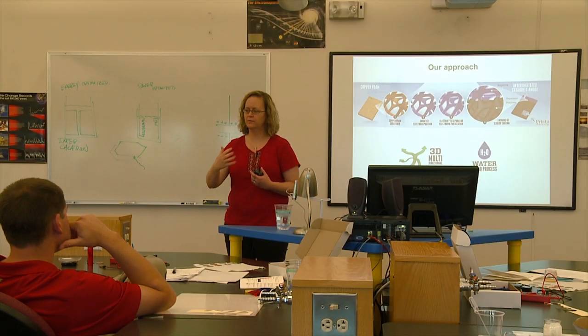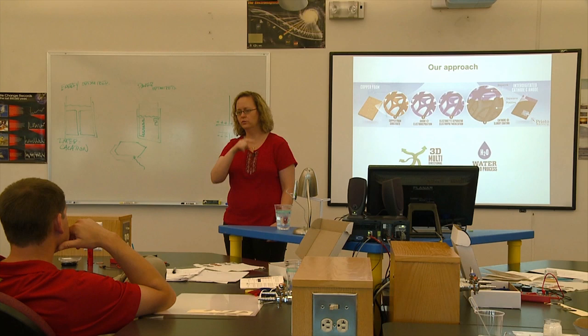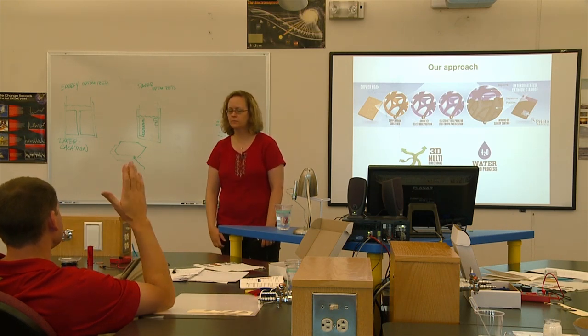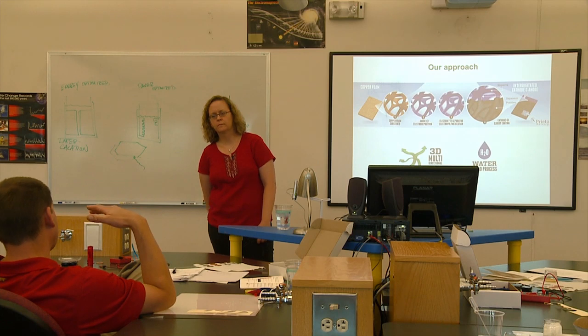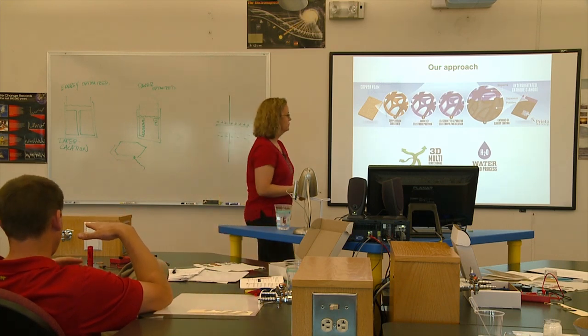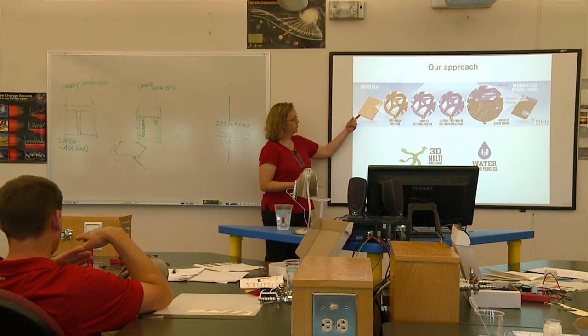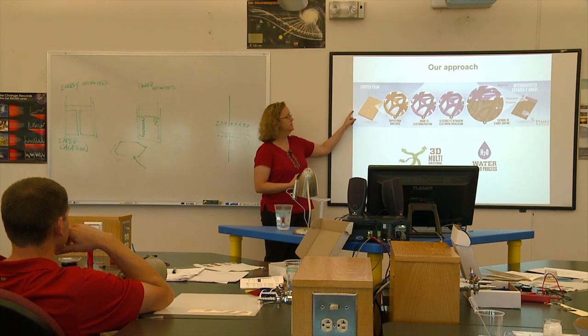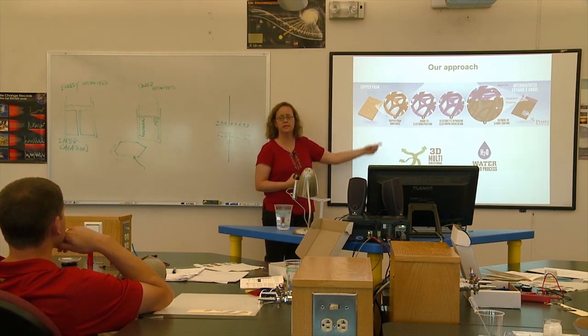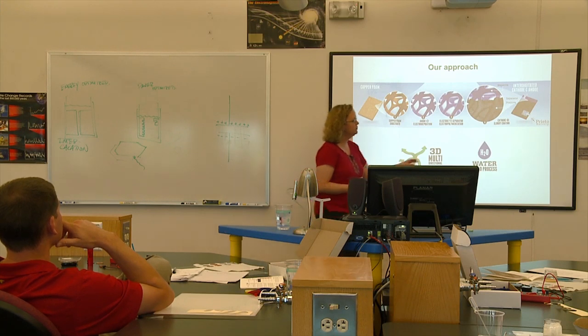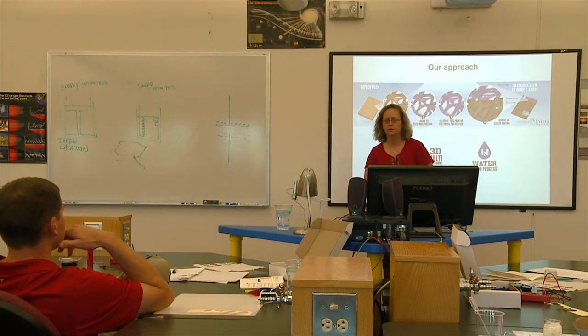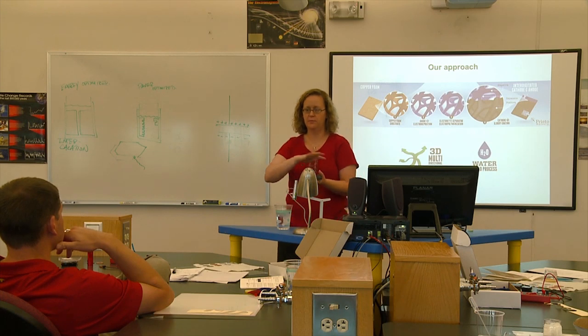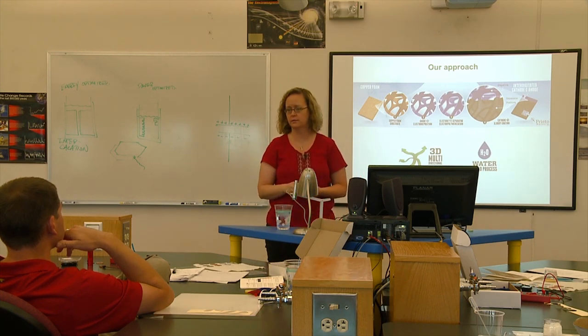And we tried to make it all kind of inline testing, and we tried to make really quick tests where you could find a mistake over very large surface areas without having to look at every part of it. So at some point in there, then you connect a lead to the copper sponge into the outer surface of the black. Actually, what this picture is not showing you is we first put a contact here that we ultrasonically weld, and that is the contact that we use for all the plating, and then it stays as the contact at the end. And then at the very end, we put an aluminum mesh, and then we put the black ink stuff on top of that also, and it dries, and those are your two contacts.